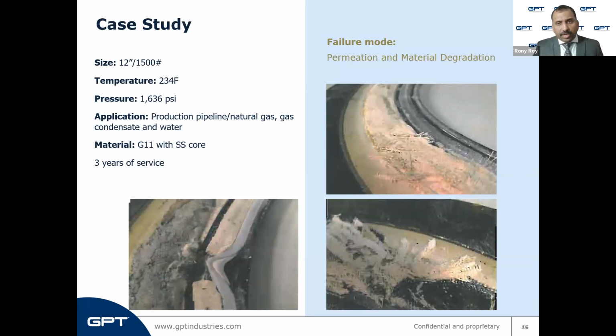N-butane was the most prevalent chemical in the pipeline makeup. The thermoset glass reinforced epoxy receives a not rated certificate for this chemical at 225°F. Greater than 20% swelling will occur with a greater than 50% loss in tensile strength. This confirms why the G11 delaminated. G11 is a type of GRE grade which is used for manufacturing these gaskets.